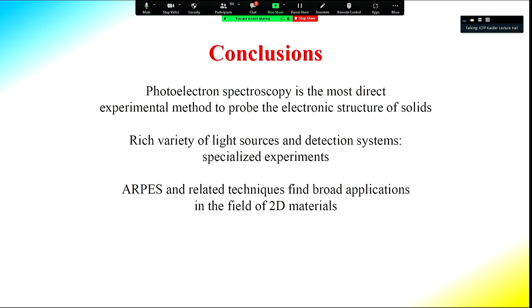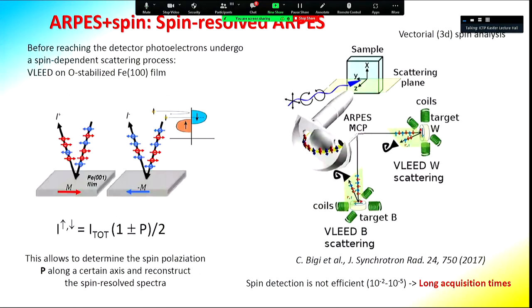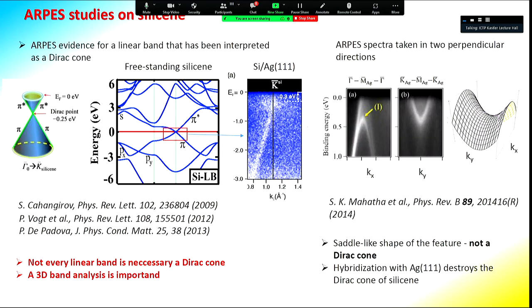Thank you very much, Paulina. There were very nice examples. Starting from the example of silicene on silver — one of the points of this talk is that ARPES is a very powerful technique to get the band structure and directly connect with theory. But there are a lot of technicalities — photon energy, sensitivity to the surface, the substrate — and we really have to pay attention when doing calculations not to jump to the conclusion that we can directly describe what is measured experimentally.